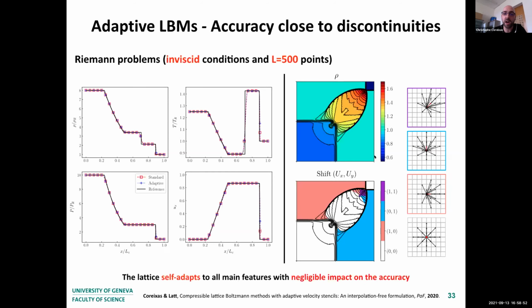Looking at the 2D Riemann problem, we can clearly see that even if small oscillations appear close to the transition between two different lattices, at the end of the day we obtain results that are pretty satisfactory. And to me, the most important thing is that this is achieved even by relying on a pretty naive way to compute the numerical equilibrium when it is missing, meaning that at the interface between two lattices, you need to reconstruct the equilibrium.